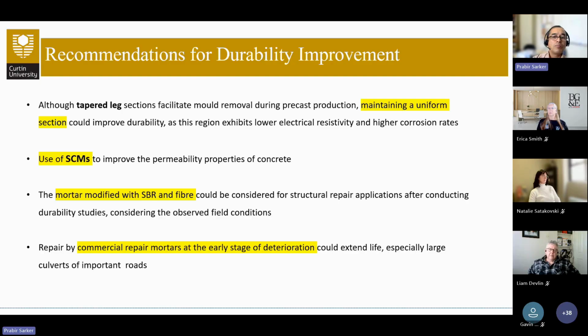If we draw some recommendations for durability improvement based on this study, from the physical observation of the culverts, I found that some of the culverts are tapered, with the lowest thickness at the bottom of the legs, and we have seen that this is also the most critical location in terms of soil and water salinity and high corrosion activity.